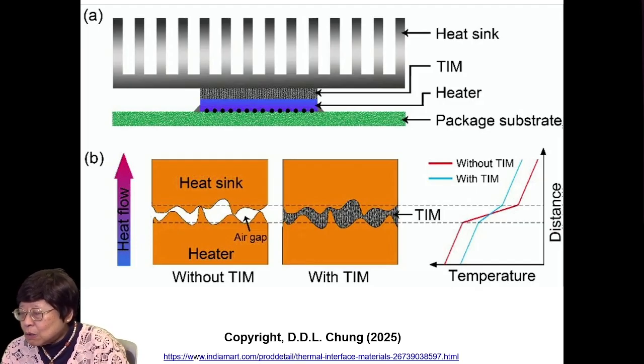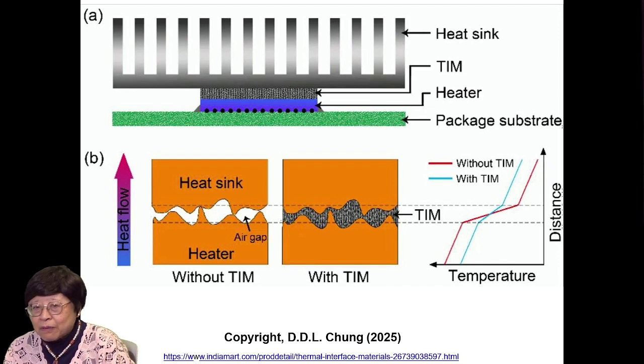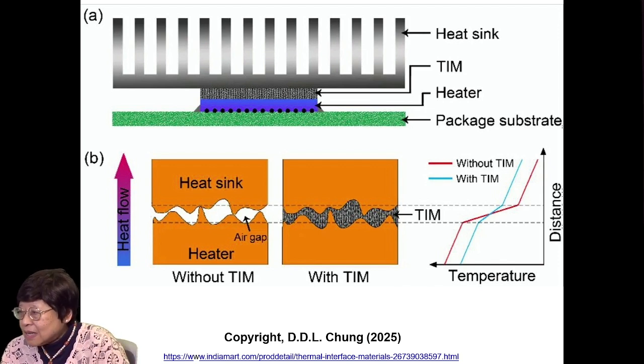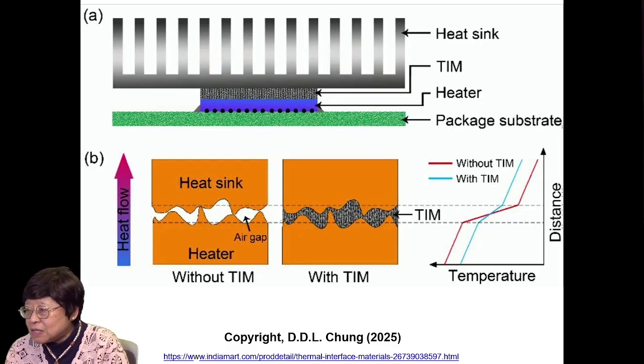When you have without the TIM at the left and with the TIM on the right, you see that the thermal resistance at the interface is diminished, so that the temperature drop at the interface is reduced when you have the TIM present, as opposed to the TIM not being present. So the measurement of the temperature drop, as shown on the right diagram, is one way to measure the thermal resistance of the interface. That's describing the effectiveness of the TIM.